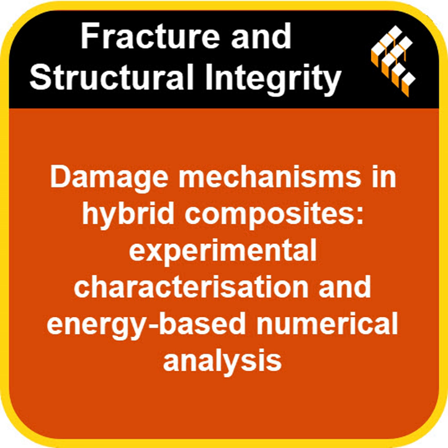The researchers think that was from individual fibers snapping one after another, especially in the carbon fiber layers on the side that was being squeezed during bending, the compression side. Oh. Where the load is applied, there's a lot of stress concentrated, and because carbon fibers are a bit more sensitive to being compressed, they tend to break in sequence, causing those little dips and rises in the force measurement. Okay, that makes sense. Sequential failure.